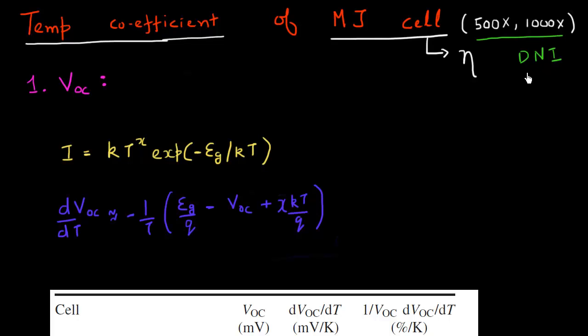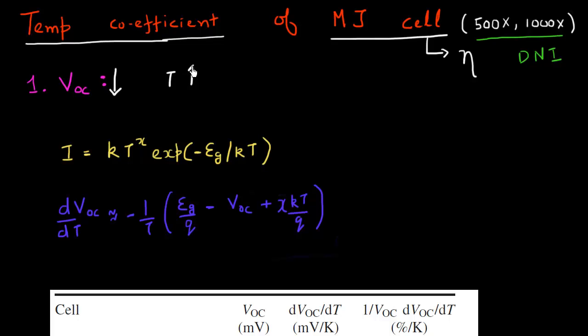This is where you expect high concentration of direct sunlight, and the ambient temperature in those places is supposed to be higher as well. So the question is whether the high efficiency these cells have will evaporate if temperature increases. The first thing to look at is the open circuit voltage, VOC, which degrades as you increase the temperature of the device.